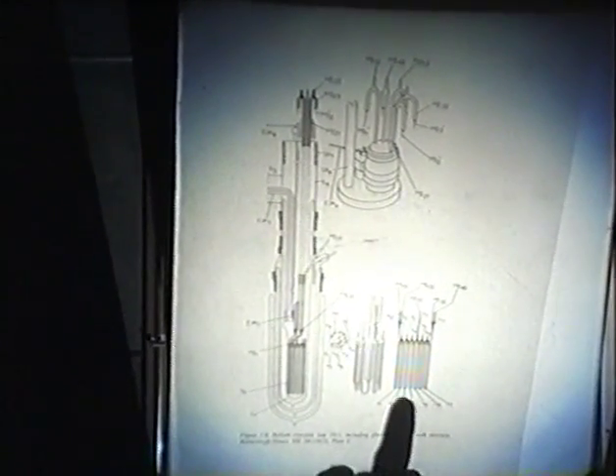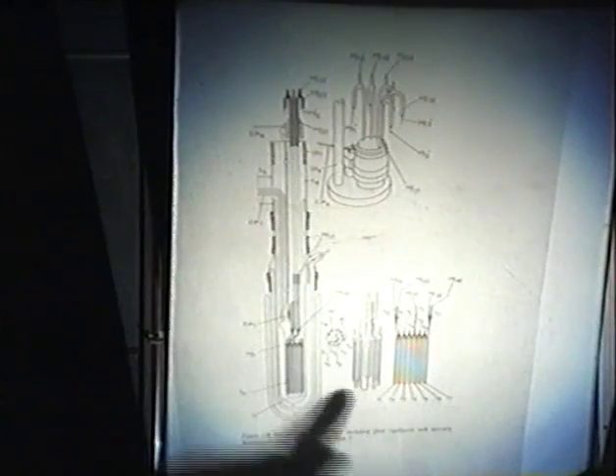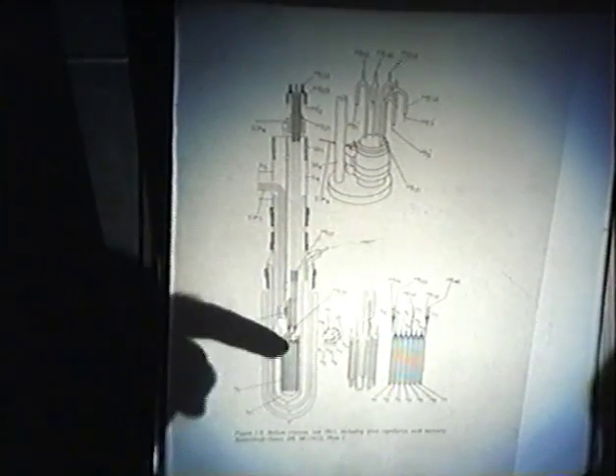They made little mercury capillaries by tipping mercury into glass tubes and then freezing it, being very careful to avoid contamination. This shows one of the mercury capillaries used in the experiment, and it's all coiled up and put down inside the helium dewar with leads connected to it to measure the resistance. And they began to lower the temperature, and of course if you've got a little bath of liquid helium, you can lower the temperature below its boiling point by just pumping away the vapours above it to lower the pressure, which lowers the temperature, and this was the result.